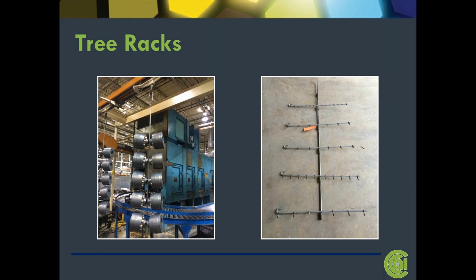To take it one step further, if you look at the picture on the right, we've got a stem, and we've got multiple crossbars. And you'll notice that some of the crossbars are different. If you go all the way to the top and you look at the first crossbar, there's about a dozen hooks on that top one. And if you come down, then there's 6 hooks, and then 6 hooks, and a dozen. And the reason I'm showing that is that with having a stem that has adjustable sockets, there's a lot of flexibility that can be gained.